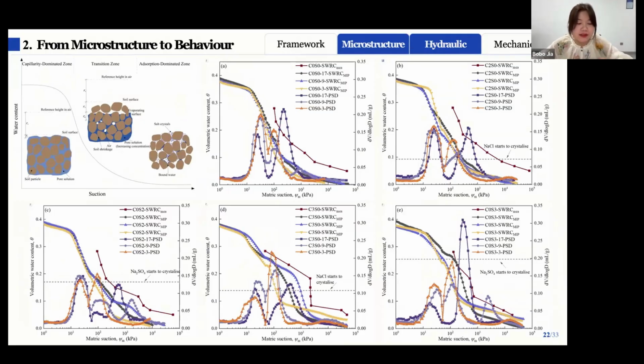And at the early stage of the drying, for samples containing soluble salts, high concentration salt solutions form more stable water films between soil particles through the salt bridge effect, which can enhance the interparticle bonding, leading to slower pore shrinkage and stronger water retention at the same water content. And as drying proceeds, the salt concentration increases until crystallization begins. At this stage, two main effects can be observed.